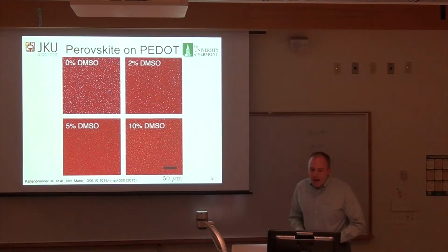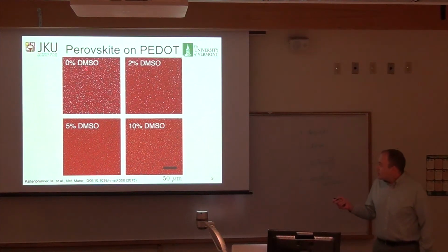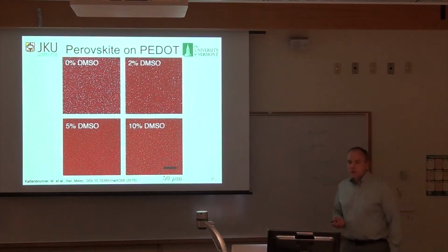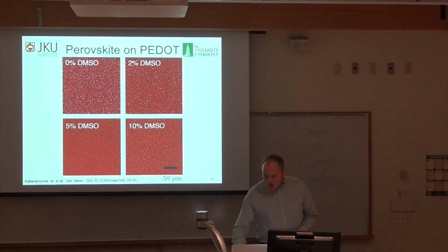What we see is that by adding DMSO, a little bit at a time, to the PEDOT, we can wind up with very uniform perovskite films. The DMSO has an added bonus that it increases the conductivity of the PEDOT itself by a factor of 2. So if we're trying to use it as a transparent electrode, now we can get working devices over very large areas reproducibly, with high conductivity electrodes.